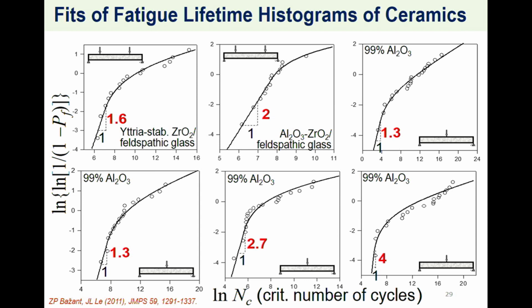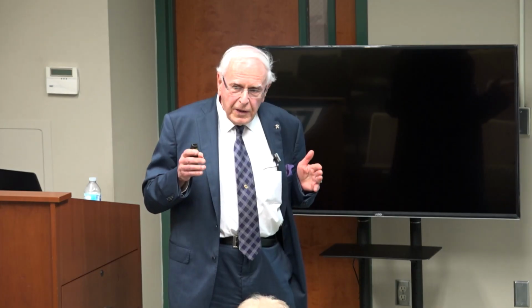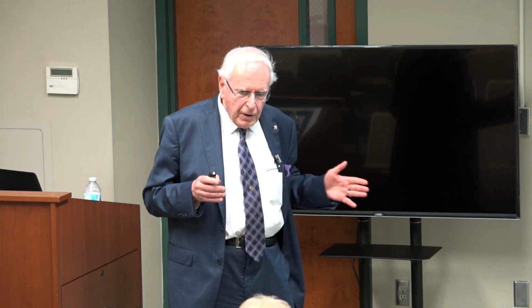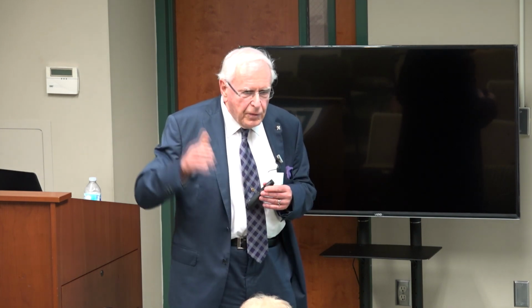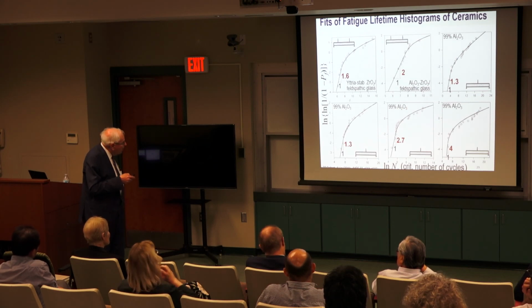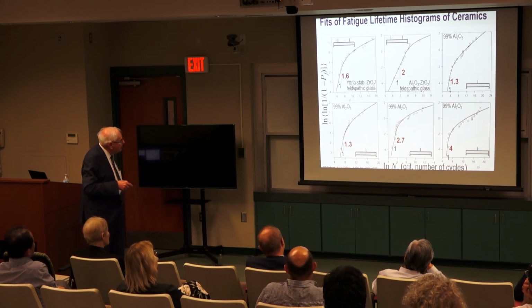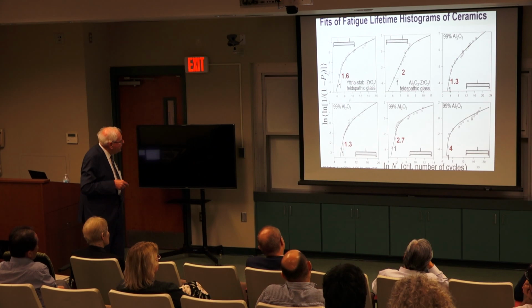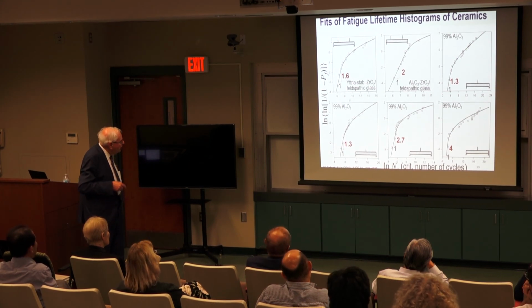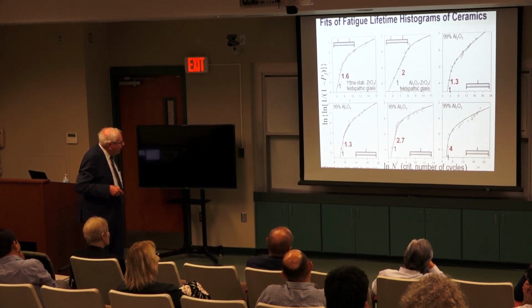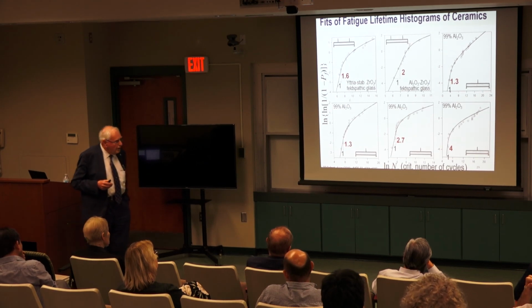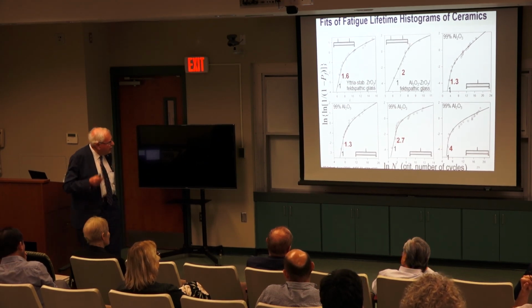If the structures are perfectly brittle, lifetime will be Weibull, so it will be a straight line in this scale. Why? Because again the structure fails where the first element fails, right? So it's like weakest-link statistics. But what is observed in quasibrittle materials are these transitions, which you can fit exactly. You see that the exponent now is not 40, it's very small, and that means for lifetime the size effect is extremely large.